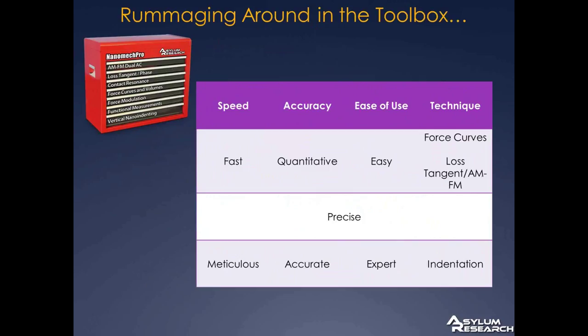Of course, we would all like our nanomechanical measurements to be fast, easy, and very, very accurate. In general, accurate nanomechanical measurements, as with other kinds of measurements, are difficult to perform. There are many experimental parameters that need to be carefully calibrated, and even with careful calibration, the experimental uncertainties can still be quite large. I made this little table as a sort of map of the trade-offs associated with various measurement techniques. Basically, the faster the measurement, the speedier, if you will, the less accurate and the more susceptible it will be to artifacts, calibration uncertainties, and other inconveniences.